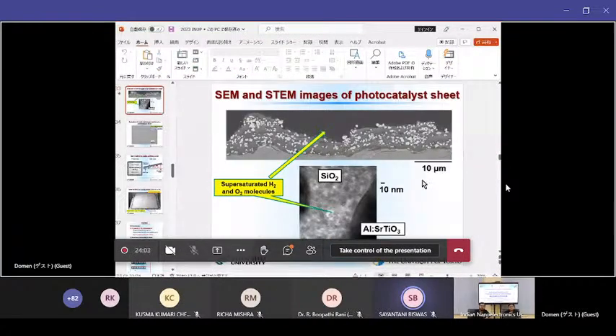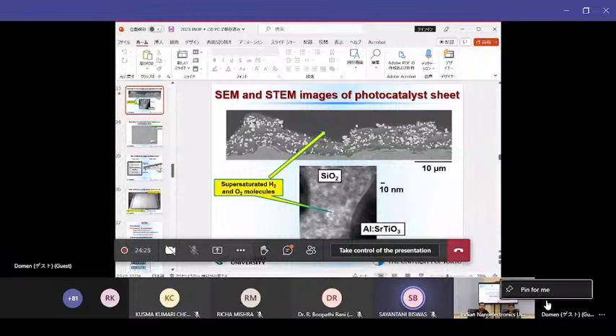In the case of the one-step water splitting system, as I showed here, this is 10 micrometer. This is the photocatalyst layer, so less than 10 micrometer thickness. We also tried to make thinner or thicker layers, but 10 micrometer is enough to get the optimum activity in this case.